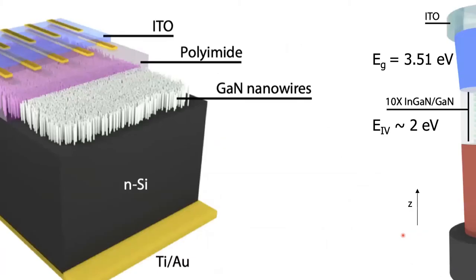So what I want to describe is the work that we've recently published on this gallium nitride system. Gallium nitride has this large band gap of 3.5 eV. It was grown by molecular beam epitaxy in Zetian Mi's group on a silicon substrate. There's a forest of gallium nitride nanowires. Inside each nanowire, there's a set of 10 indium gallium nitride quantum dots. So indium is put inside there. That decreases the band gap, how much depends on how much indium is there. These are approximately 2 electron volt band gap quantum dots.